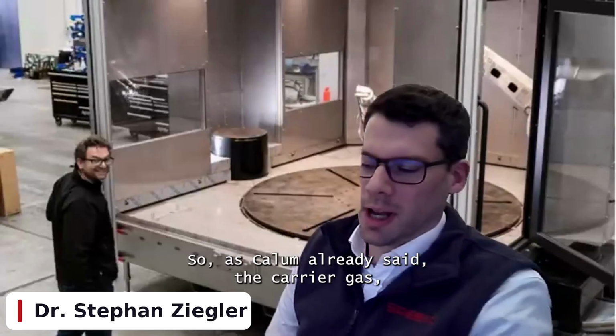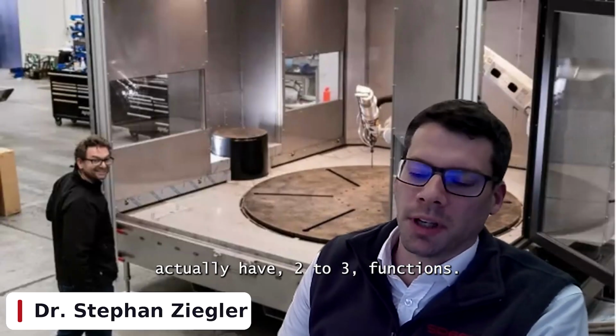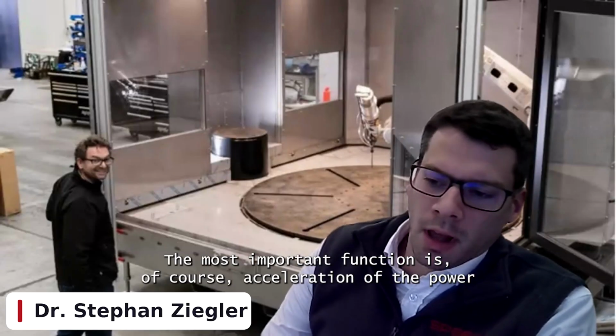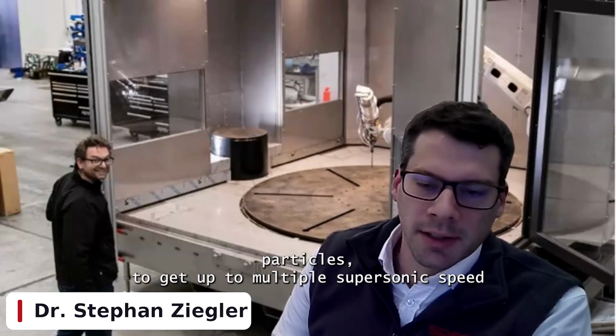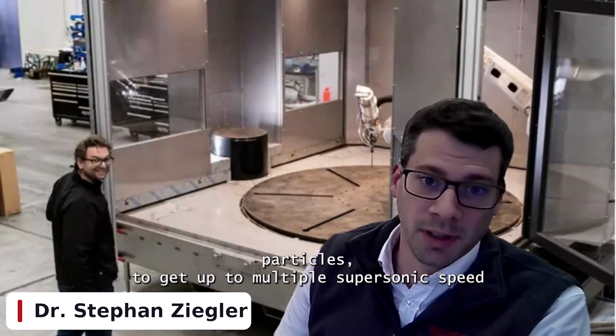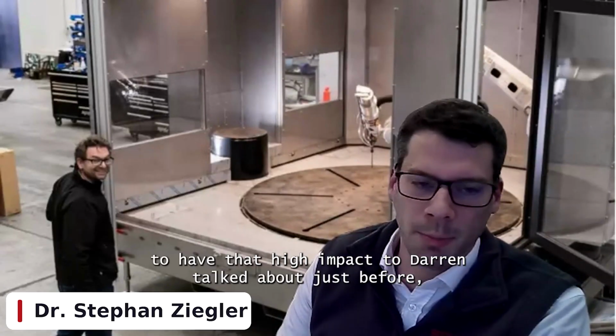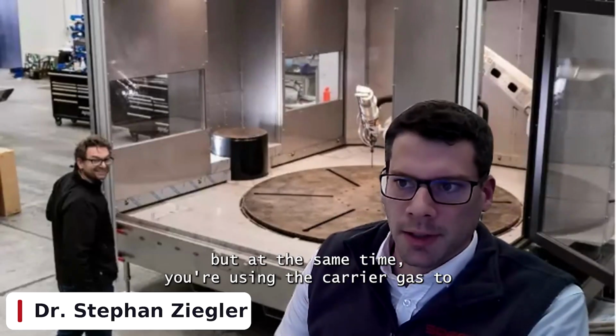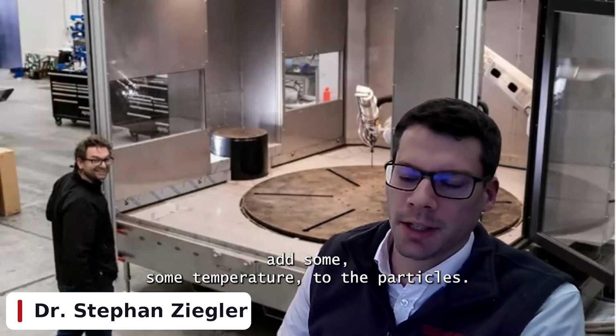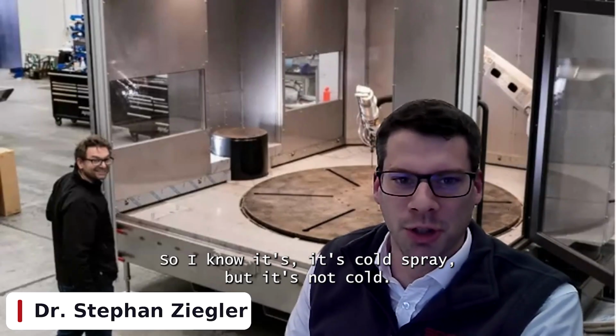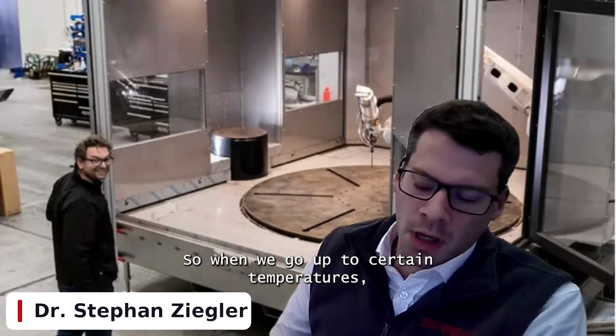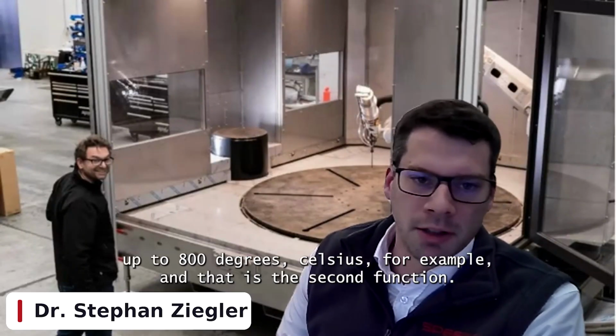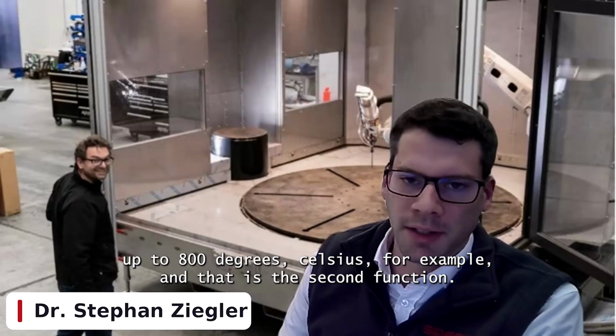Yeah, sure. So as Calum already said, the carrier gas actually has 2 to 3 functions. The most important function is, of course, the acceleration of the powder particles to get it up to multiple supersonic speed to have that high impact Darren talked about just before. But at the same time, we are using the carrier gas to add some temperature to the particles. So I know it's cold spray, but it's not really cold. So we go up to certain temperatures, up to 800 degrees C, for example, and that is the second function.